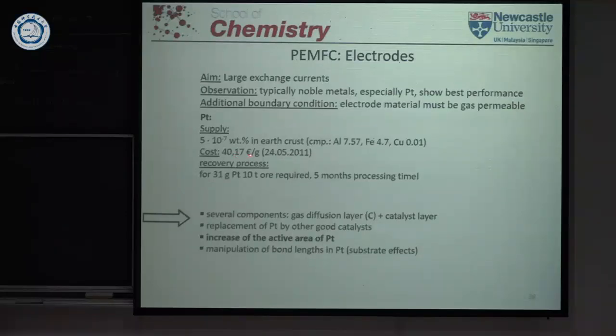Costs are pretty high, 40 euro per gram. That's about, I don't know, 300 RMB per gram, roughly. A lot of money, right? The way it's being made is also complicated. For 31 grams of platinum, you need 10 tons of ore, and you have a processing time of 5 months. So making platinum as a raw material is expensive because it's not very abundant, and it's very complicated and takes a long time to make. This is something one has to have in mind when you say, okay, let's take platinum. You can take platinum in the lab, but when you want every car in China to be equipped with a fuel cell, then you run into a problem with platinum.